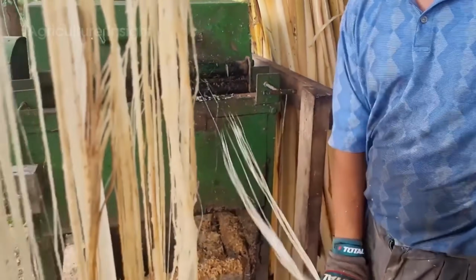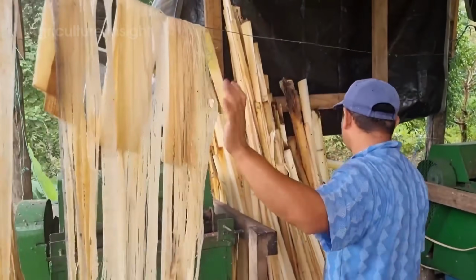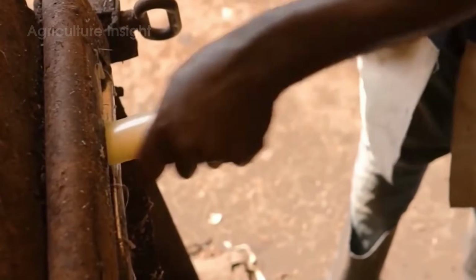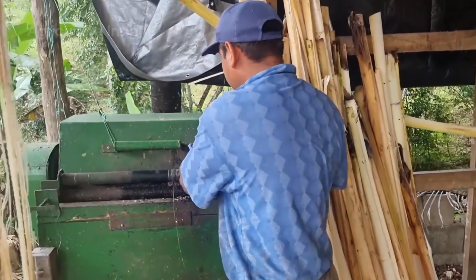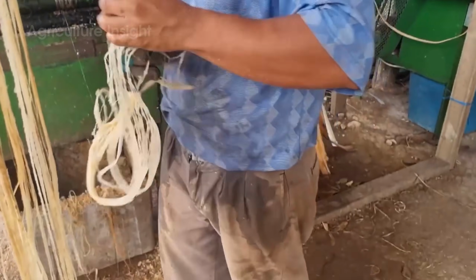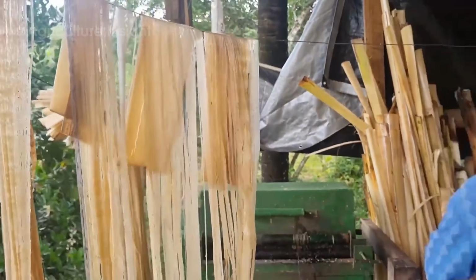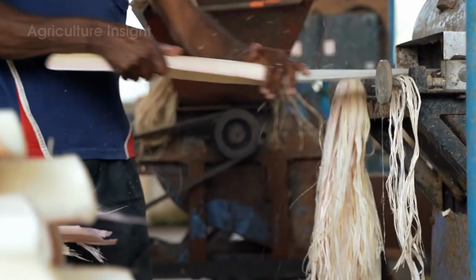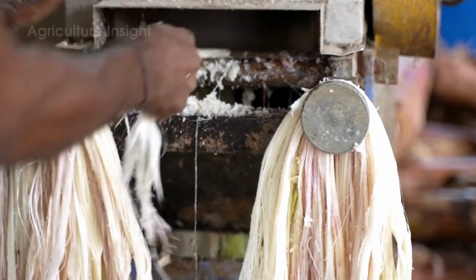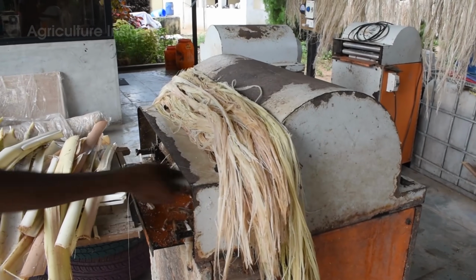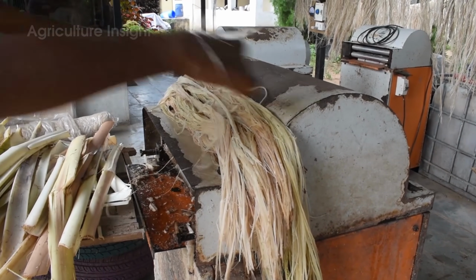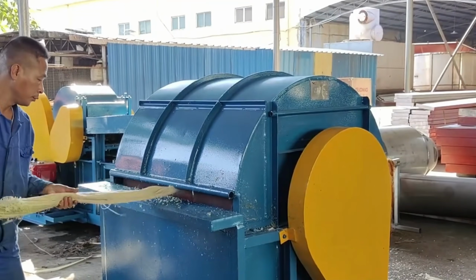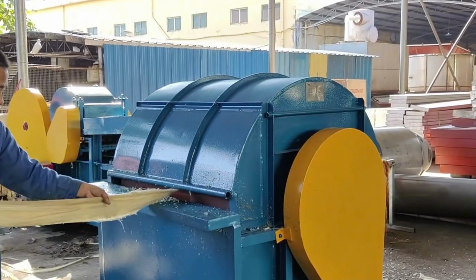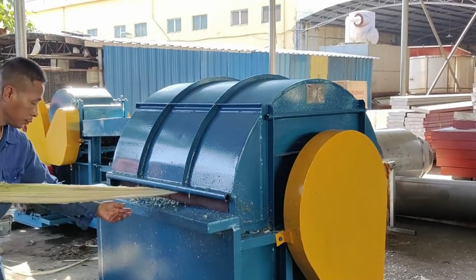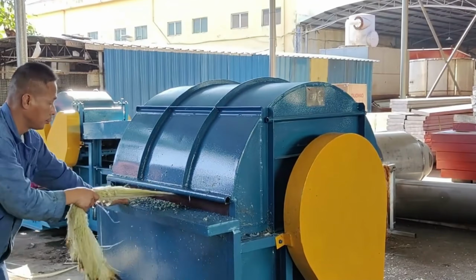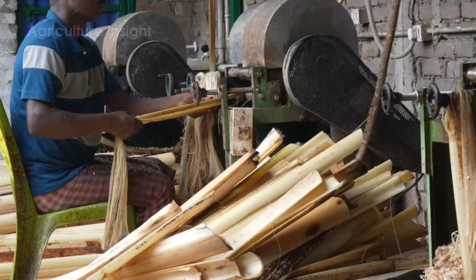Each banana sheath is fed through a mechanical press or a manual stripping table to remove the soft pulp, leaving behind long bundles of cellulose fibers. Steady hand movements and precisely controlled pressure prevent the fibers from breaking, producing rough fiber strands with a characteristic ivory color. In practice, this work is far from easy, as the worker's sense of pressure combined with a consistent rhythm is a skill that often takes years for newcomers to master.